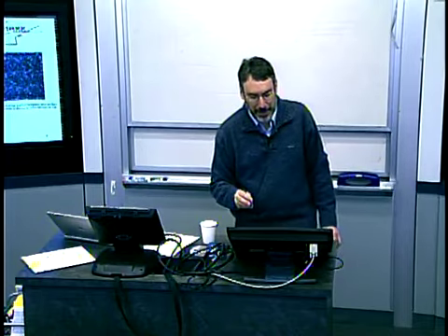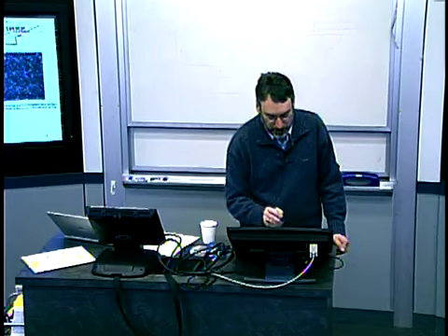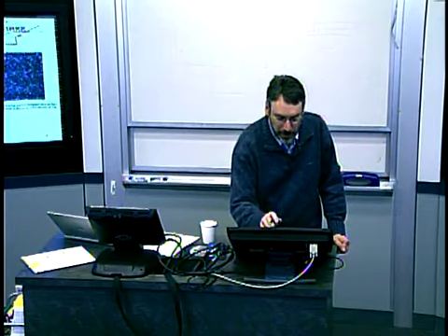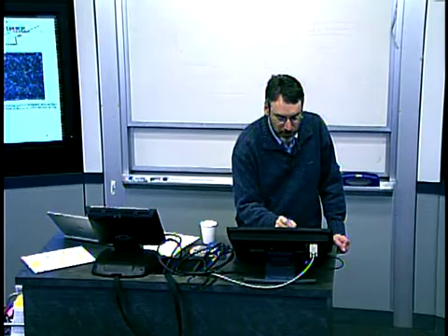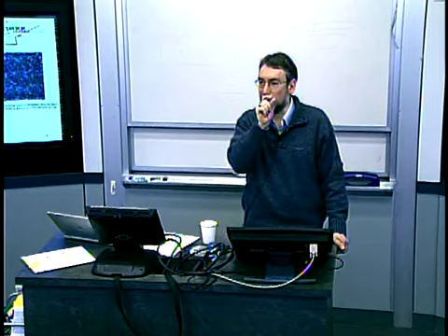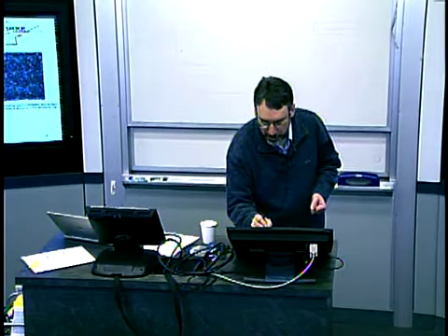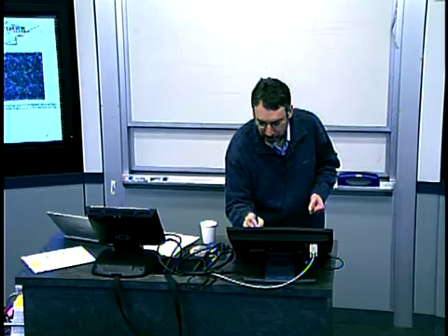Now, I believe what they're doing in this paper is really just looking locally after the deposition and looking to see what percentage of volume is missing in that little indentation resulting from the conformal deposition, and looking for fairly high, near 100% step coverage, so that there's not a missing percentage of the feature compared to, say, one of these large structures that might have a very high missing volume.